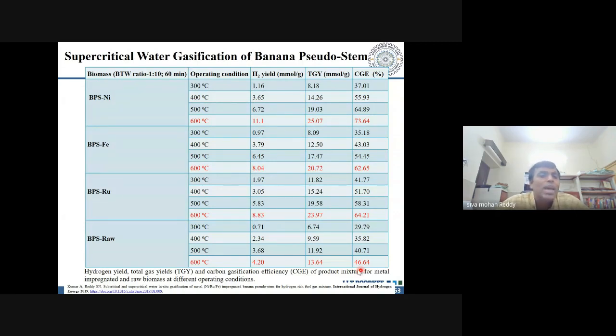Now, as soon as we are introducing the nanometals into your biomass matrix, you see there is a huge jump in your hydrogen yields from your 0.7 to almost 11.1 millimole. That means almost 11 or 12 times higher than the actual gas yield, sorry, 3 times higher than your raw biomass yields. That is at 600 degrees centigrade.